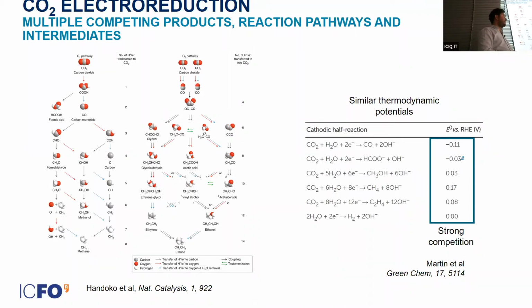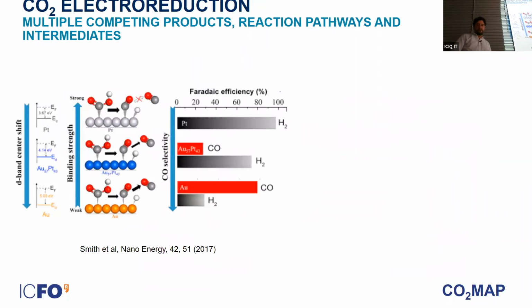So the voltages that in principle will be required to transform CO2 into carbon monoxide, formic acid, methane, or ethylene are really within the same range. There's a strong competition in the thermodynamic domain, and there is a strong competition in the kinetic domain too. Now, there are different strategies to manipulate this catalyst and try to improve a given reaction.